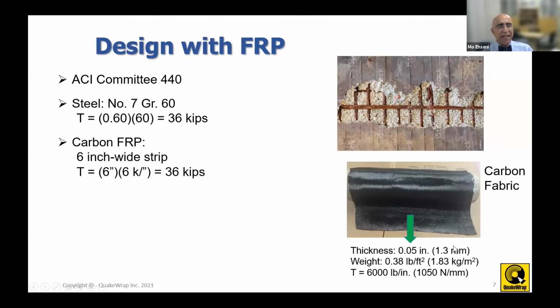And if you put a layer of this carbon fabric on the surface of the same wall, this particular fabric has all of the carbon fibers in the orientation of that green arrow. So if you took 1 inch or 25 millimeter of this and test it, you see that it breaks at about 6,000 pounds every 1 inch.